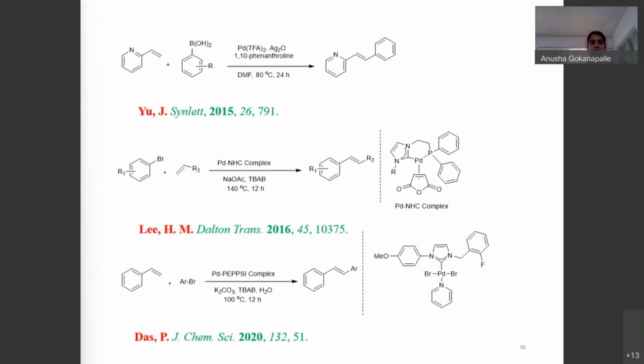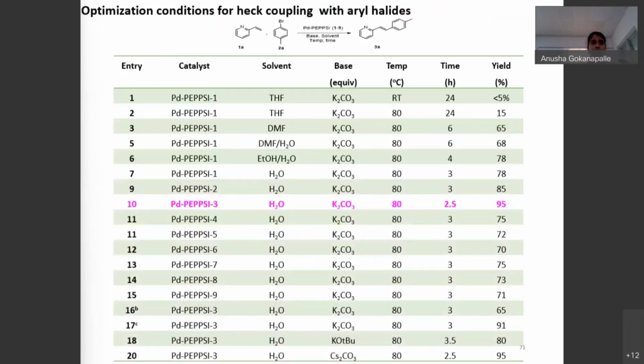These are the reported methods in the literature reports on Heck coupling reaction. Here we applied Palladium PEPPSI complexes for Heck coupling reaction. For that we have taken 2-vinyl pyridine and bromotoluene as a model reaction. First, we started the reaction with Palladium PEPPSI 1, and we got lesser yields at room temperature.